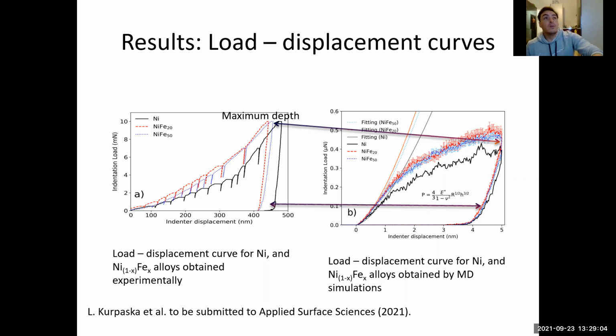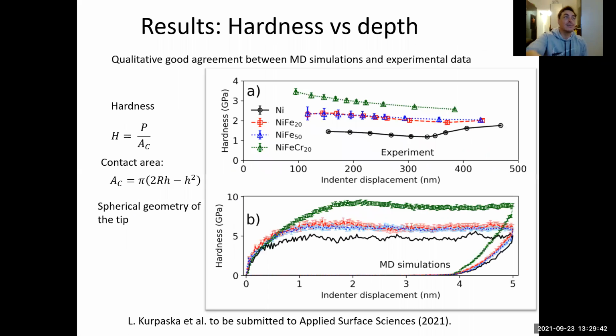And now we are also interested in the elastic recovery of the material. Here you have the unloading process, well defined. And also in the MD simulations, you have the unloading process and the elastic recovery of the material. And even here we have the pop-out, and also the pop-out here. This is something that we figured out in the daily discussions between experimentalists and theoreticians, which are sometimes really fantastic. These discussions are so great.